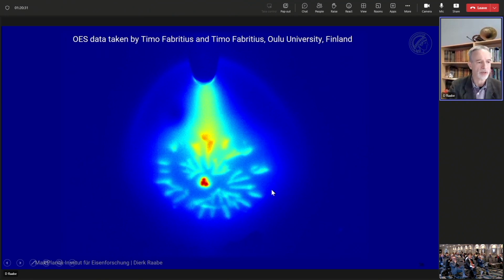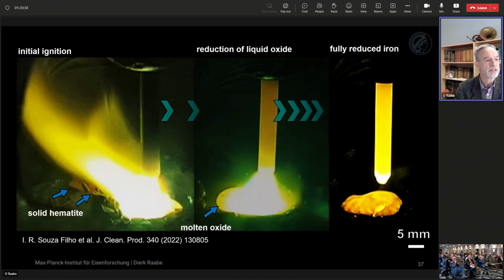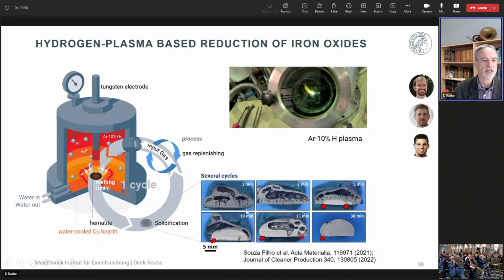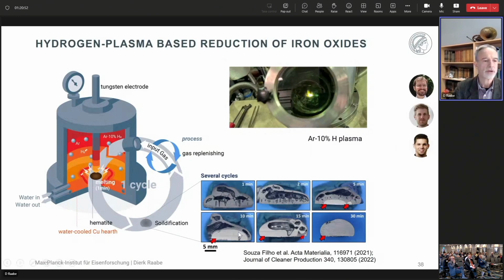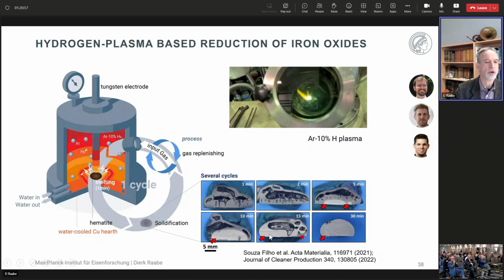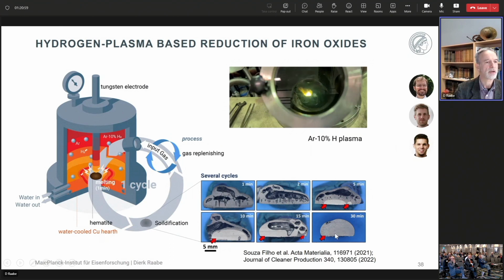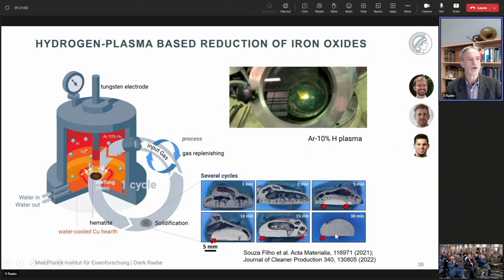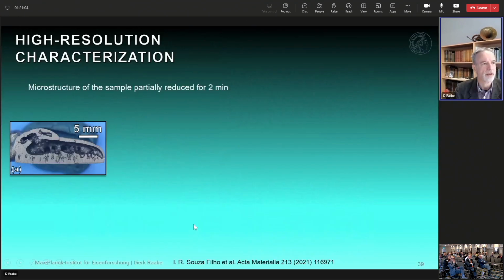That means, in other words, when you want to do proper plasma theory, you must really do non-equilibrium theory, which is not trivial. Then we interrupt these types of experiments, as you see here, take out the samples and analyze them step by step by using classical microstructure analysis. So here are the interrupted experiments that you see, and due to the weight, the iron sinks readily to the bottom. After 10 minutes, 15 minutes, you have pure iron in your hand, and after 30 minutes, everything is done. That means it's also a very fast type of reduction method.